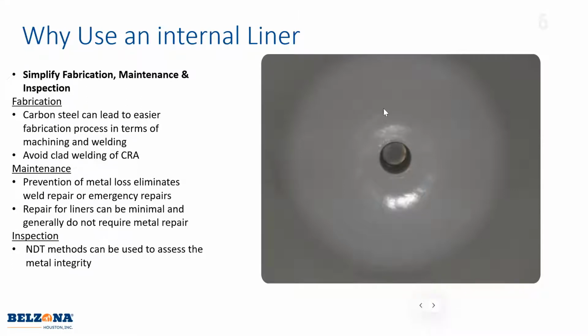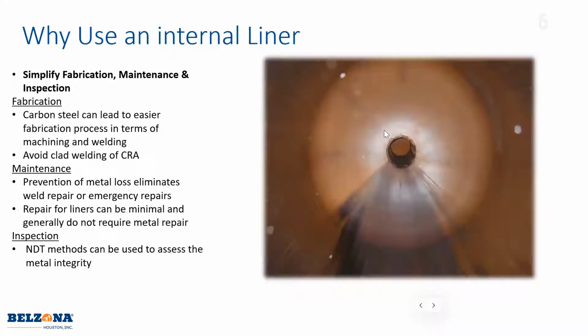So this right here is an example of a coated vessel, and this is 5 years after. So what you've effectively done is installed a corrosion allowance system. So instead of adding more metal for your corrosion allowance, you put a liner. So this is 5 years after. So you've effectively stopped 5 years of corrosion. Most of our liners, when they're fit for service, you're looking at a 10 to 15 year lifetime. And that doesn't mean after 10 to 15 years, it's totally gone. That's just our recommended inspection interval.